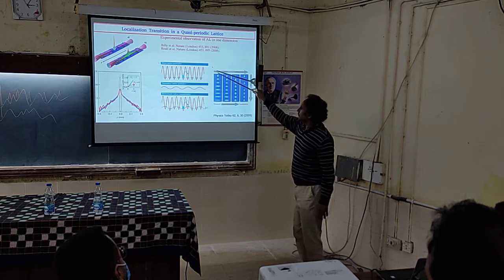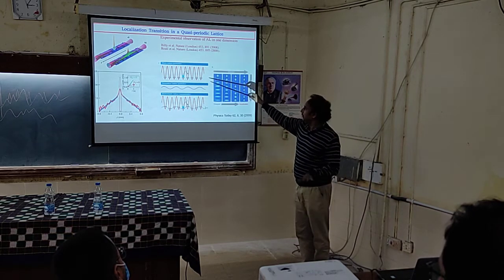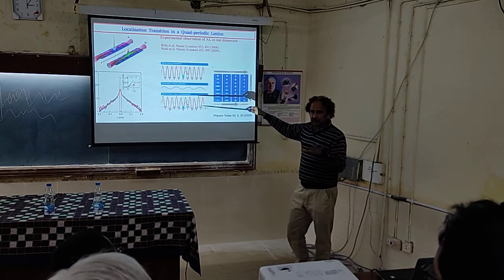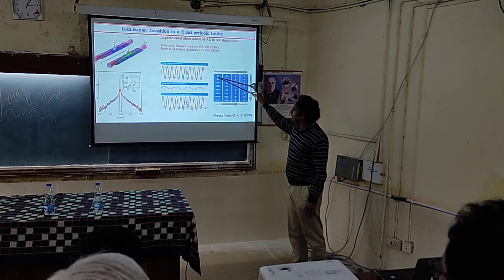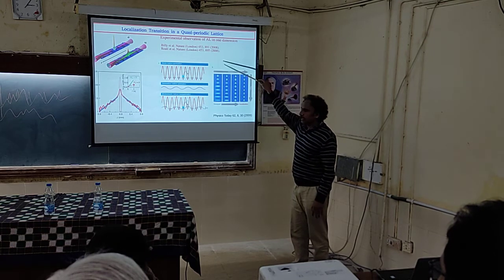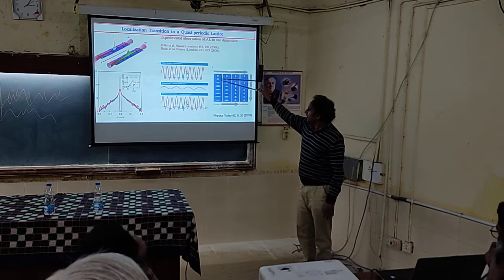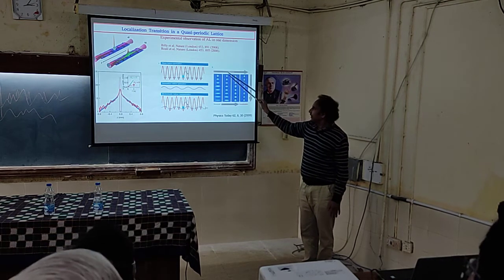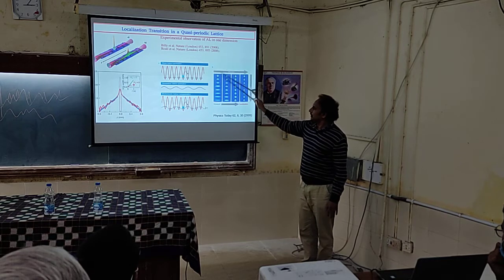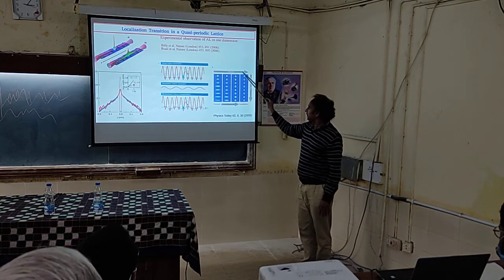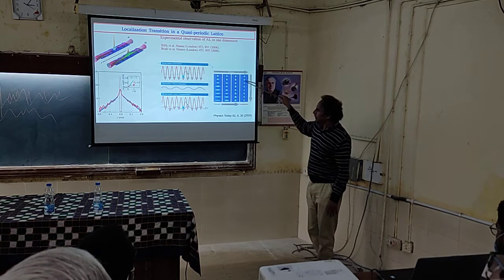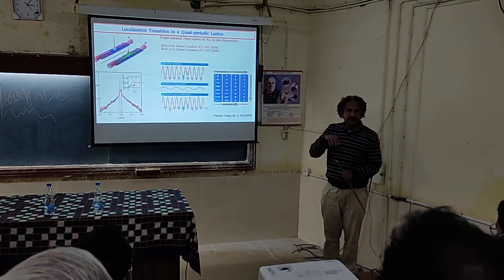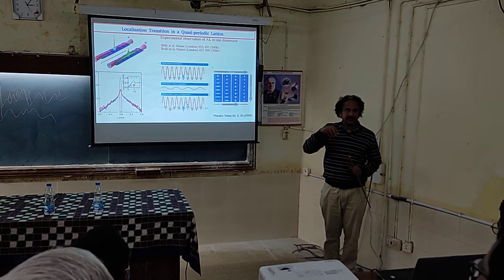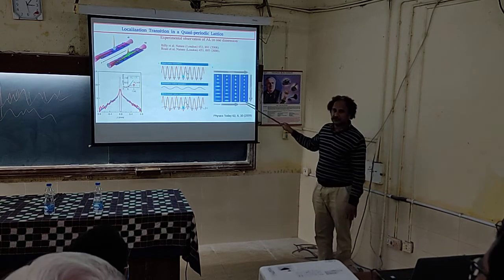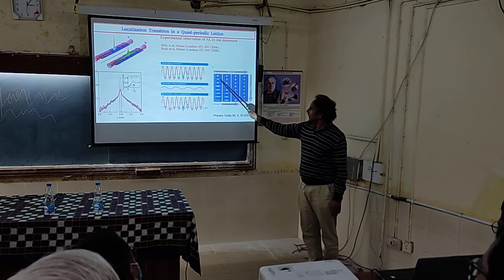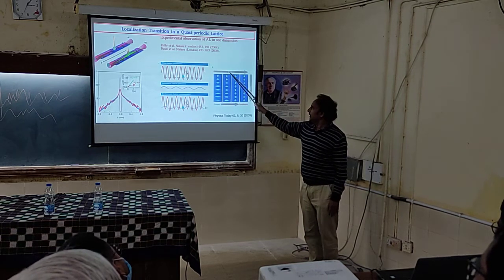And here you can see when there is no quasi-periodicity, it's a periodic lattice, without any disorder. You can see this cold atom cloud is freely expanding as time goes on. If this is time, you can see that this is spreading nicely. But the moment you increase the disorder strength, that means this W, you can see that at the end there is no spreading of this gas cloud. That means the gas cloud is trapped. So it's a localized state. There is no expansion of the gas cloud. So it's a clear transition from delocalized to localized state by simply increasing this disorder.